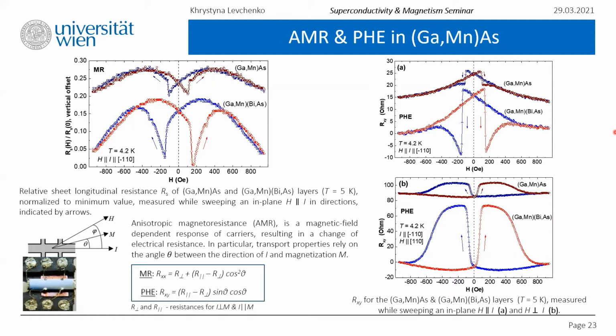For this, we have chosen ternary and quaternary compounds from the 10 nanometer series of samples with 6% of manganese and 1% of bismuth. They are all grown on gallium arsenide. As you remember, only with such a buffer, we have the biaxial crystalline strain with in-plane set of easy magnetization directions along cubic 100 and uniaxial -110 and 110. In the case of the indium gallium arsenide, we simply have tensile strain, which leads to out-of-plane magnetization along just the 001 crystallographic axis. So this is a sample.